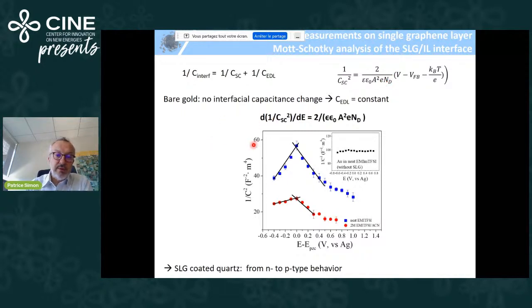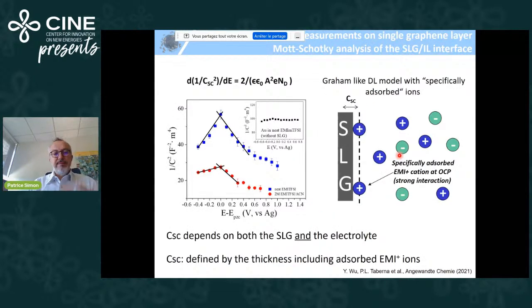So this is a plot of 1 divided by C squared versus E minus EPZC. And what you see is that in both cases, whatever solvent or no solvent, you have a maximum, and then you move from an N-type to a P-type behavior in both electrolytes, solvent-free or not. And obviously for gold, there is no change of slope because it's a constant capacitance. But okay, then you can calculate from this plot a kind of charge carrier density.